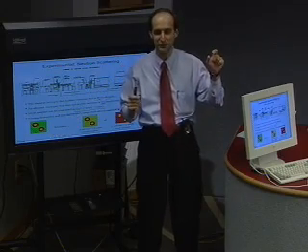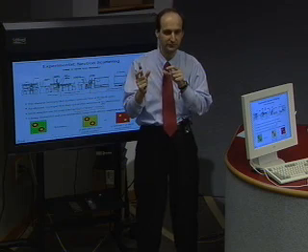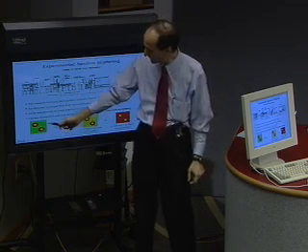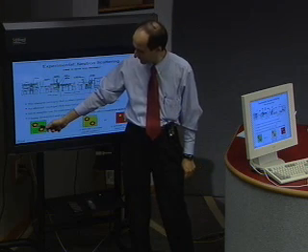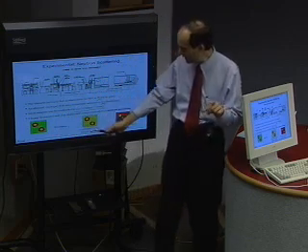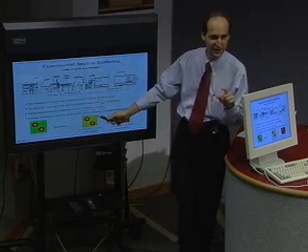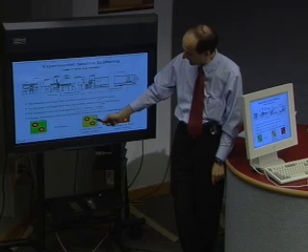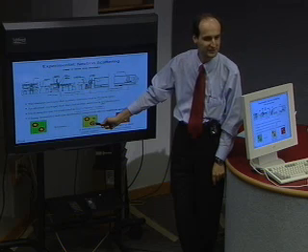Now imagine that these are micelles. Micelles have different amounts of hydrogen in the core and in the shell. If you put micelles in heavy water only, then you're going to have scattering from the core and scattering from the shell, which is going to be different. Imagine that you mix your heavy water with enough regular hydrogen, so the scattering from the heavy and light water is the same as the cores of the micelles.